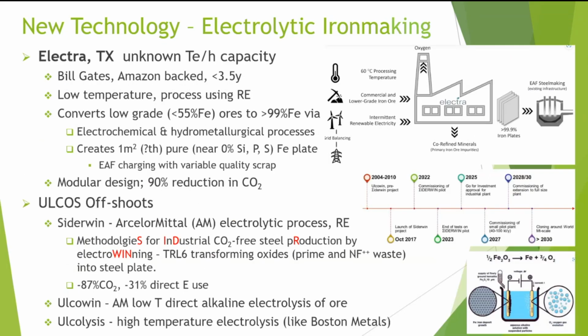Some other electrolytic processes. Electra in Texas is sponsored by Bill Gates and Amazon. It also has been up and running for less than 4 years. It's a low temperature process, and it's converting 55% iron ores to 99 plus. It's electrochemical and hydrometallurgical. It's creating 1 square meter of blocks, but we don't know how thick. And that will go straight to an electric arc furnace with virtually no tramp elements.